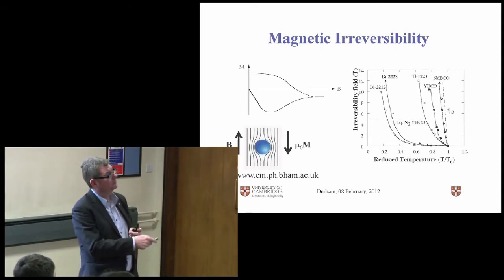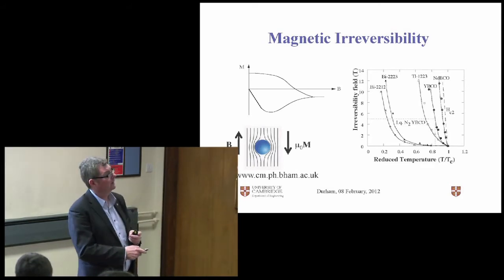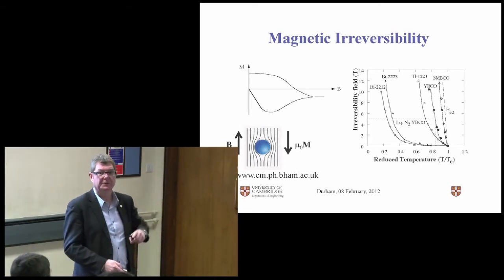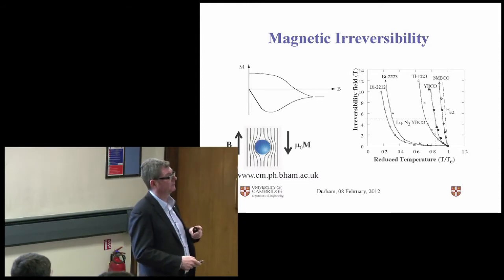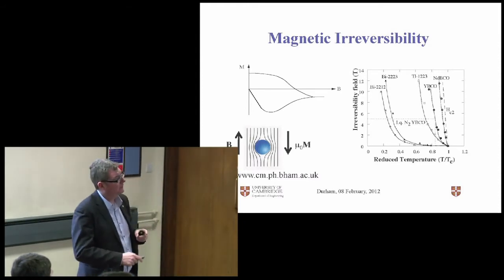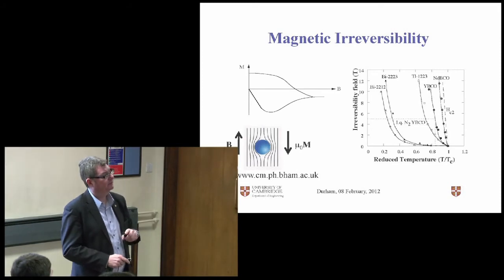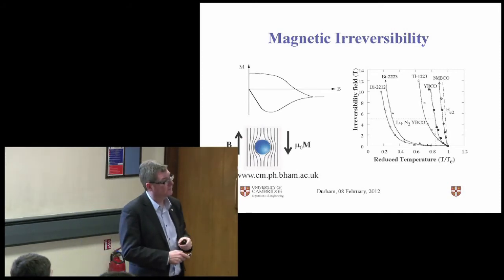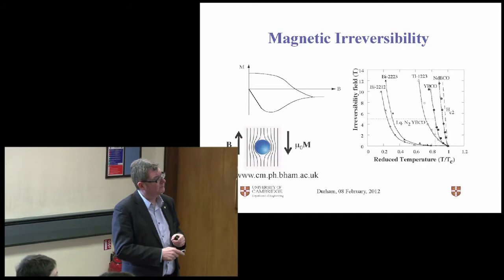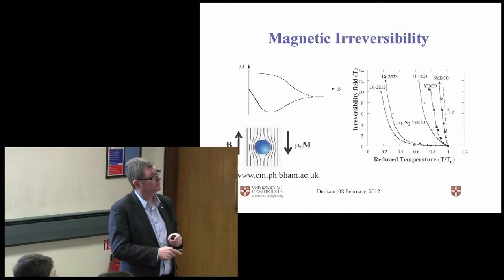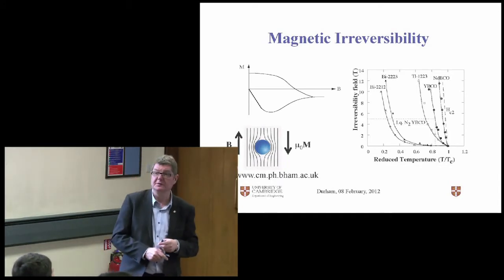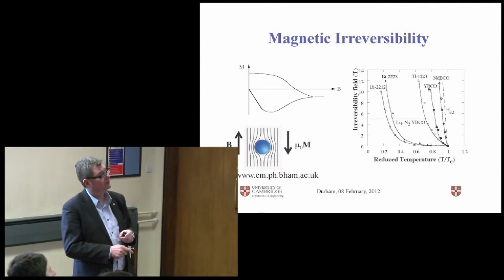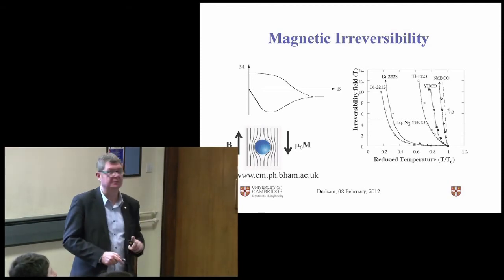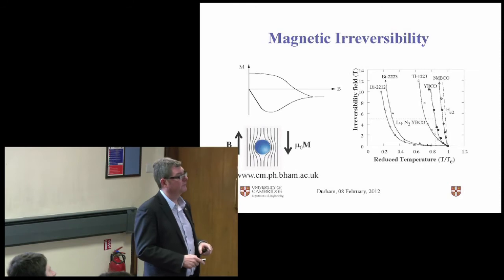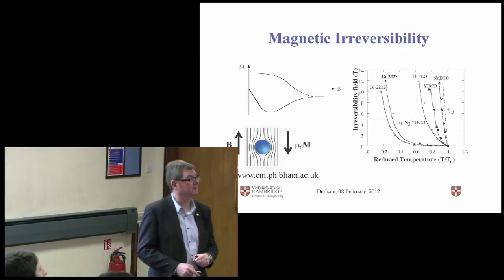So we want this hysteresis to be as wide as possible, and the stronger the pinning, the wider the hysteresis, and the bigger the field. So that's how we interpret the MH curve, or the magnetization curve of the superconductor. The field at which we get this pinch-off, where the hysteresis disappears, is called the irreversibility field. And essentially we need to be working below the irreversibility field at a given temperature if we want to maximize the properties of our sample.